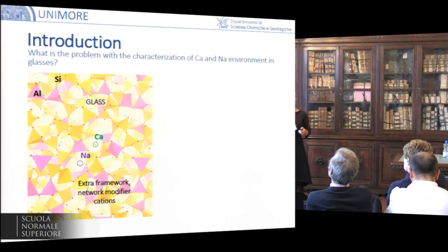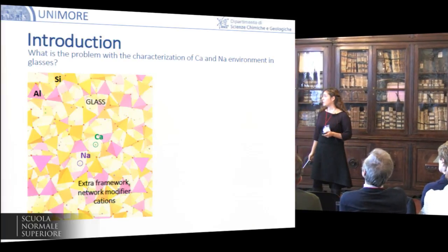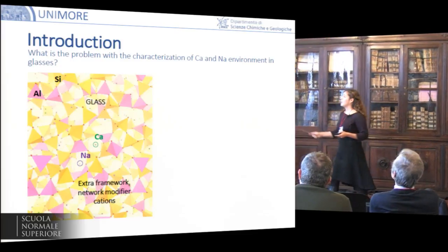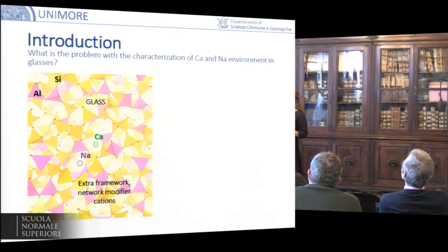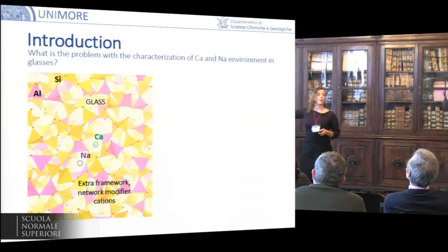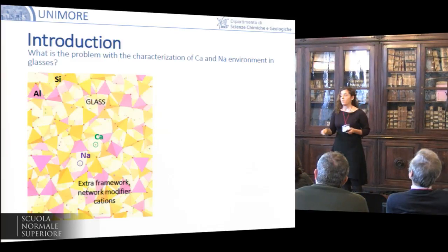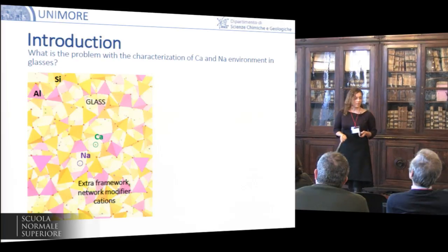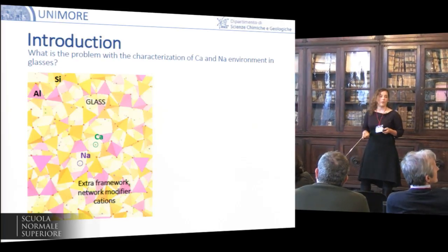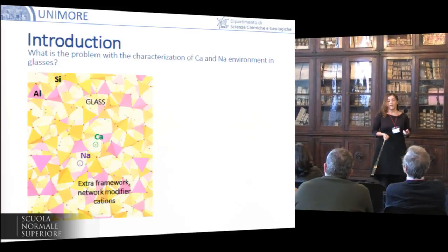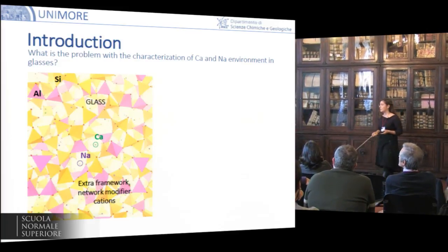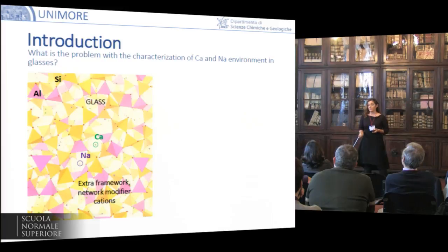And okay, now what is the problem? The first problem is that we are talking of glasses, and then we are talking of systems which lack periodicity on the medium range and on the long range, and then all those techniques that are very powerful in the characterization of crystalline and ordered phases like diffraction techniques provide very little information on these systems.